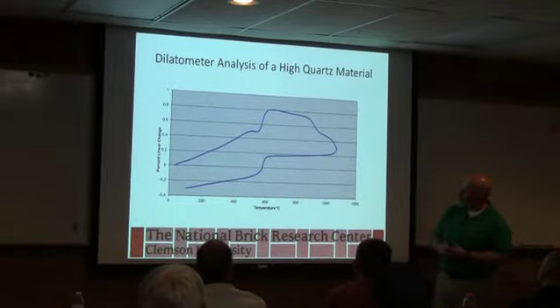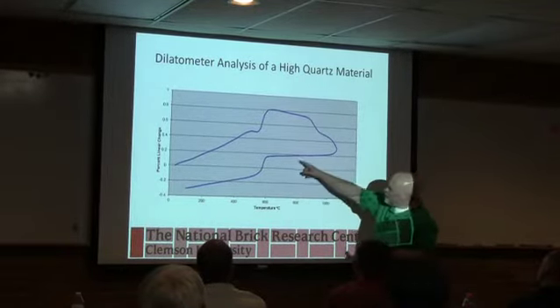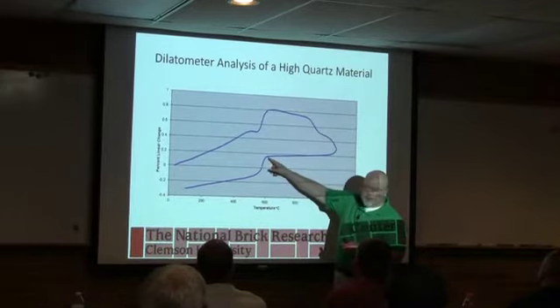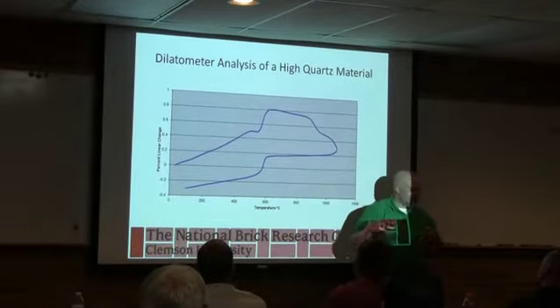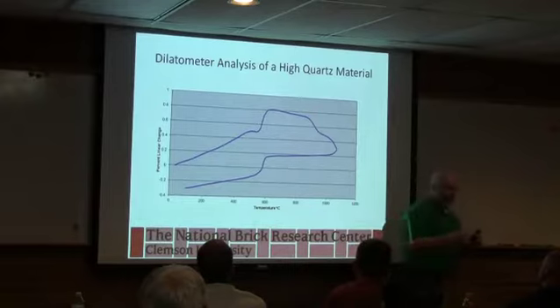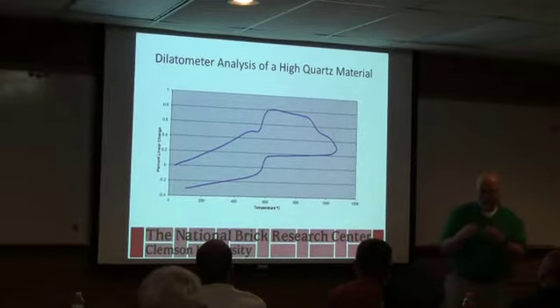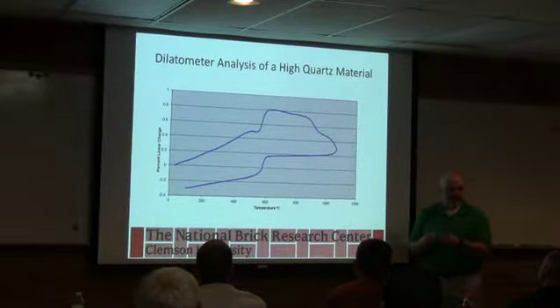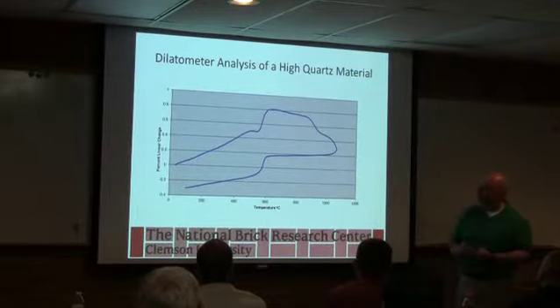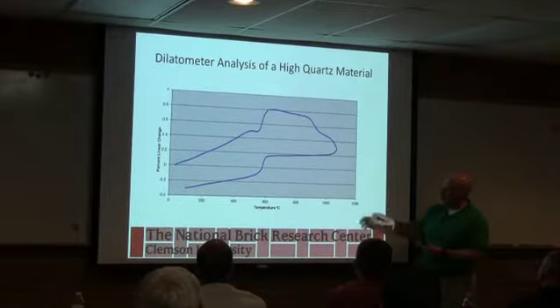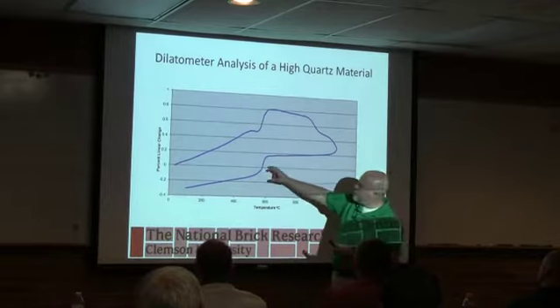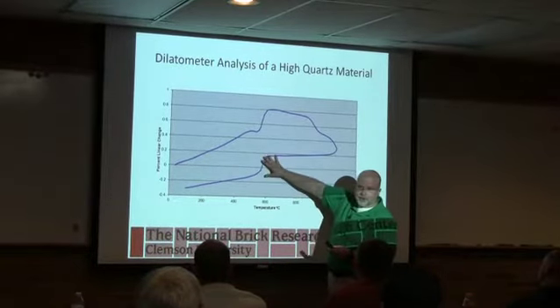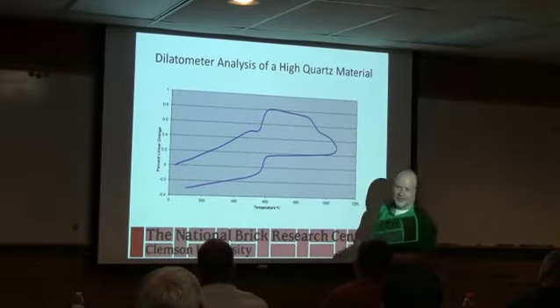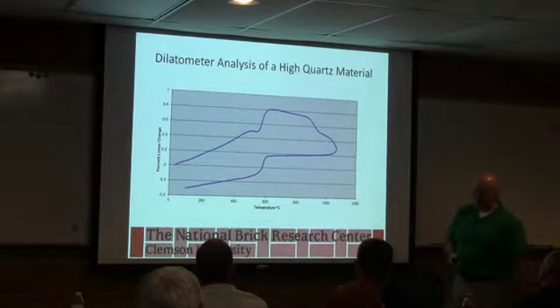Okay. By the time, theoretically, we get back to here on cooling, we've made glass. The glass is stuck to that big quartz grain, and then all of a sudden the quartz grain is going to try to pull away from the glass. And because it's stuck to it, it can't really move as much. And depending on the magnitude, you can do damage. Now, this is a material from North Carolina, and they successfully make brick out of really high quartz stuff.